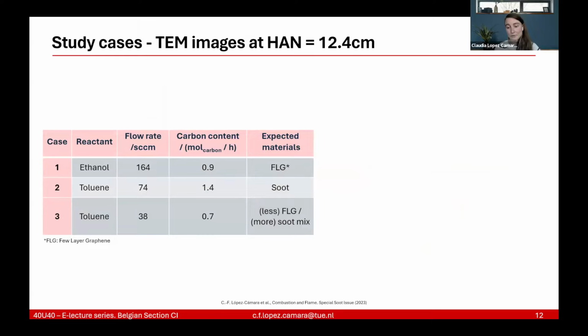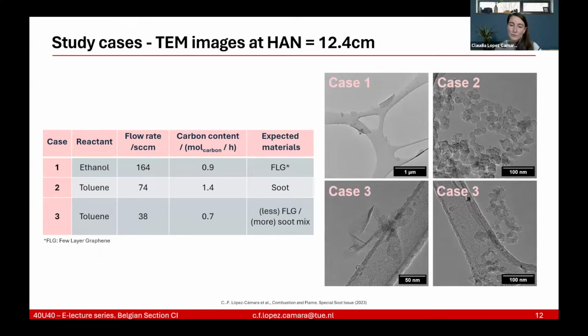And based on previous results from our lab, and also previous results from others, we knew that the expected materials based on the carbon content and on the reactant were going to be graphene, soot, or a mixture of both. But we still needed to check if that was right. And we did check it. And we saw that indeed our expectations were achieved.